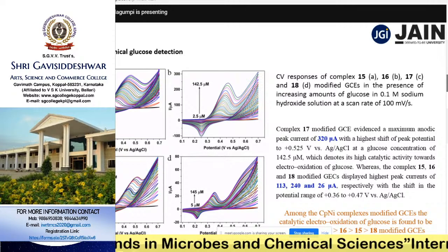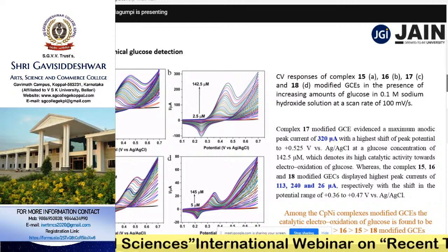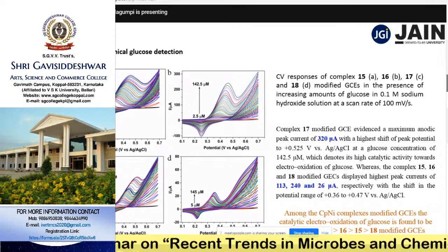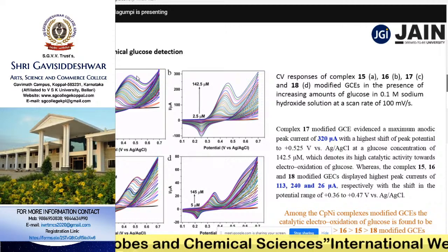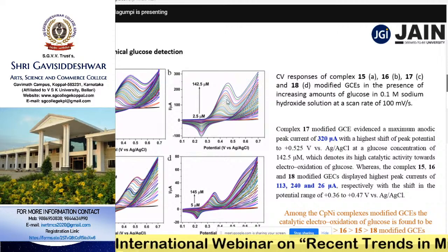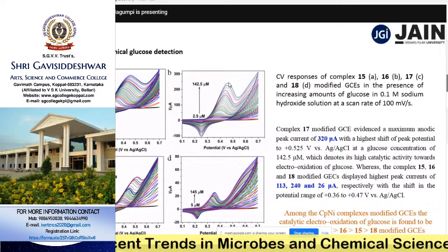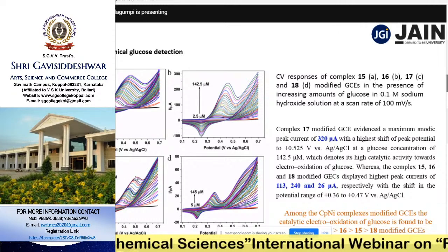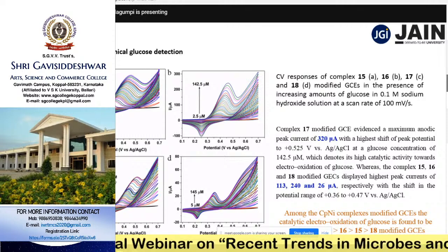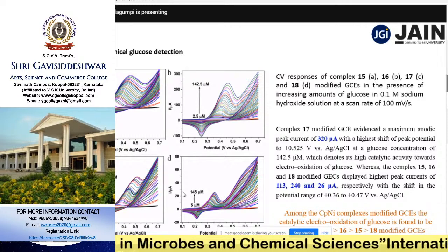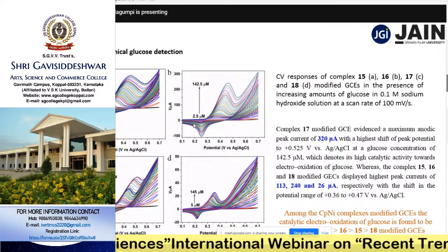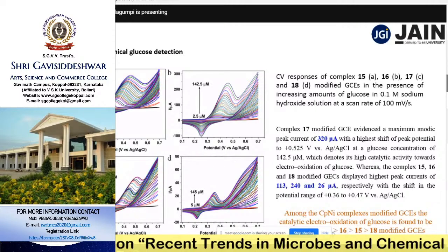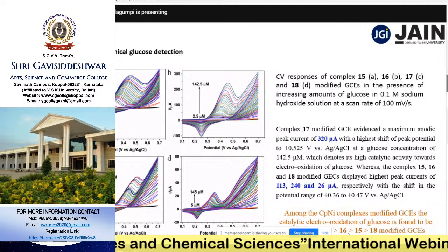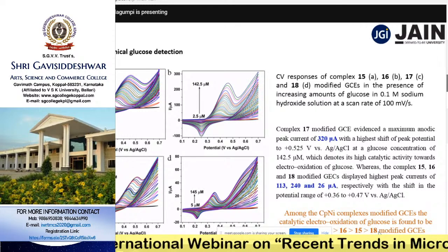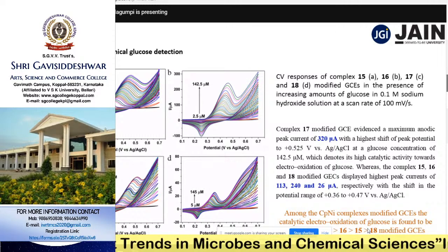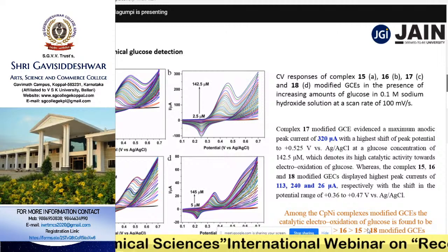This is because of the electrocatalytic oxidation of glucose using nickel complex modified electrodes. In the first case, we got current up to 100 microamps, whereas in the second case, it has gone over 200, close to 250 microamps. In the third case, we got the maximum, around 320 microamps of current at 142 micromoles of glucose, while the last case is the least active. So the activity of these nickel complexes is in this order: complex number 17 is the most active one, 16 is slightly lesser than that, 15 is slightly lesser than that, and 18 is the least active one, right?